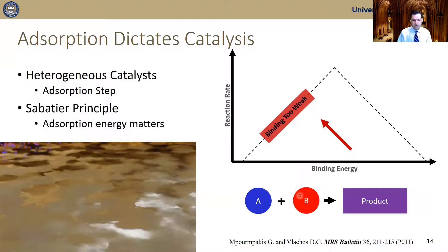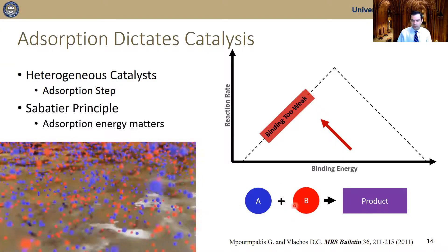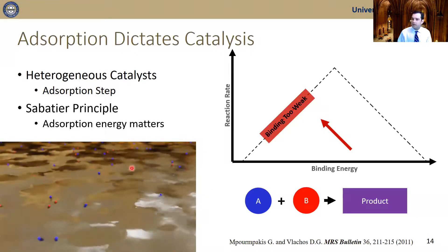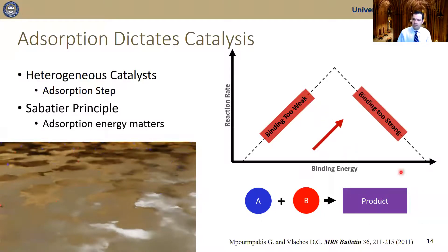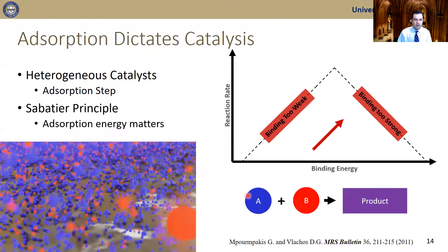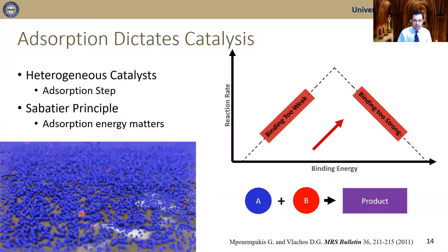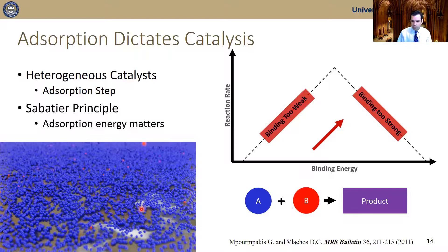Neither too weak — if you have weak adsorption of your reagents (I colored them blue and red), then they don't reside on the catalyst surface and will not react to have products. On the other hand, if you have very strong adsorption — here the blue reactant has very strong adsorption — only one reactant is on the surface of the catalyst. The red reactant does not reside on the surface, and your catalyst is simply poisoned by the most strongly bound species.